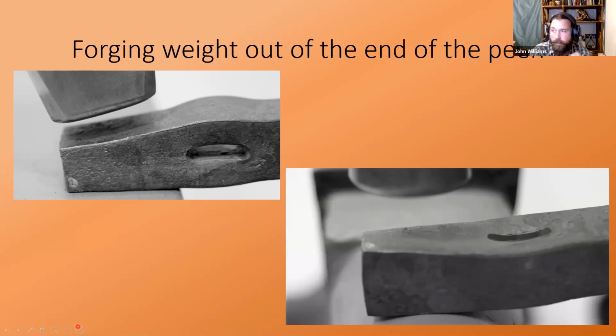And the easiest way to do that is don't let it get hot. You get it in and out of the stock before you get a transfer, and you keep the heat in your billet or in your workpiece where it should be, instead of transferring it into your punch as a heat sink, and then you don't have your punches getting really messed up. So it's better to get them in, get them out before they ever take any color.